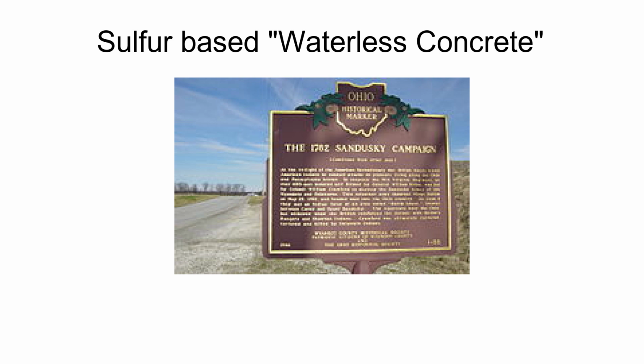Strictly speaking, it isn't a concrete as there is little by way of chemical reaction. Instead, the sulfur acts as a thermoplastic material binding with a non-reactive substrate. Cement and water are not required. The concrete doesn't have to be cured. Instead, it is simply heated to above the melting point of sulfur, 140 degrees Celsius, and after cooling it reaches high strength immediately. The best mixture for tensile and compressive strength is 65% JSC-1 lunar regolith simulant and 35% sulfur,